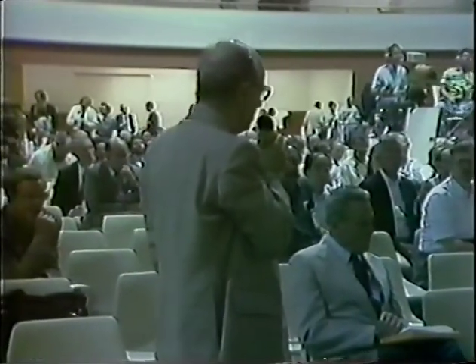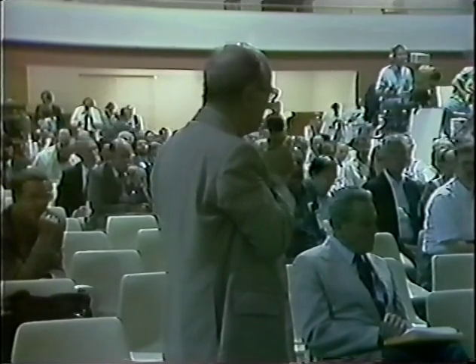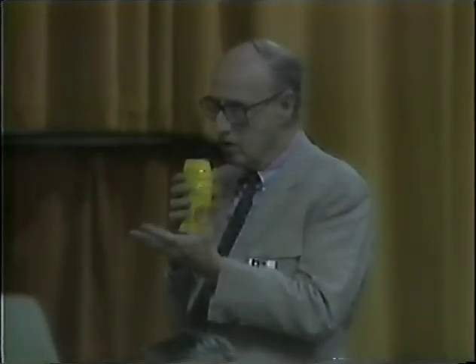Next, Dr. Bockris, please. As far as the voids are concerned in palladium, there is a poster upstairs under the name of Fuller, and this poster shows actual photographs of the voids and shows that they burst. They burst out into blisters with very considerable energy, and this also gives rise to a number of dendrite formations around the edge. And I think that as far as the curious non-equilibrium phenomenon we're talking about is concerned, this may be very important. In respect to the ratios, the highest I've ever heard of is 1.1.